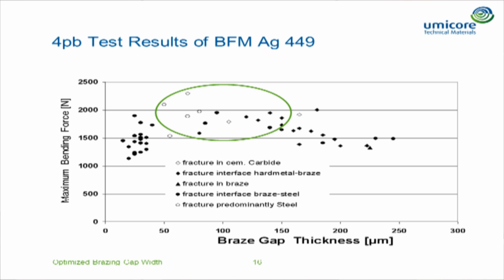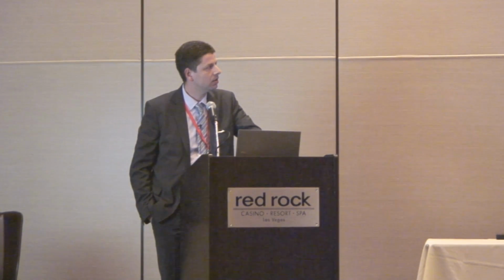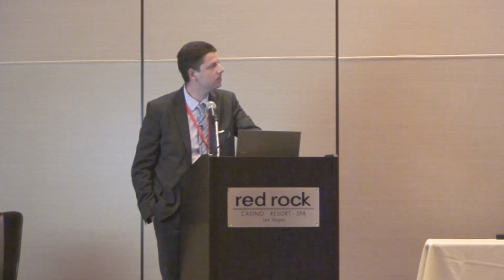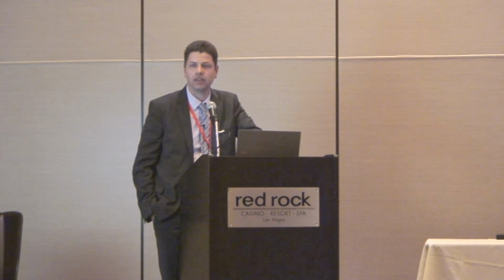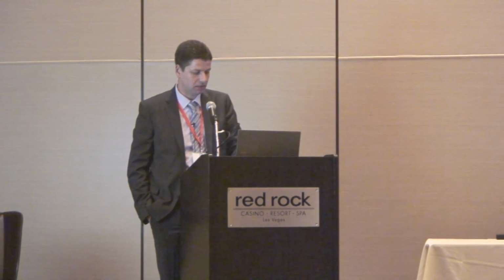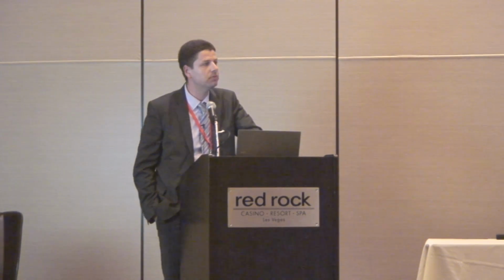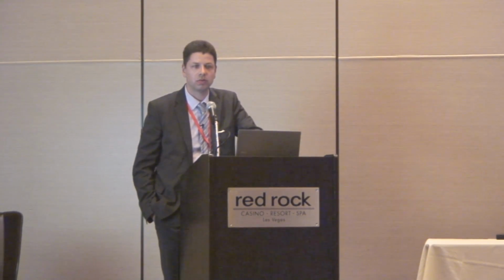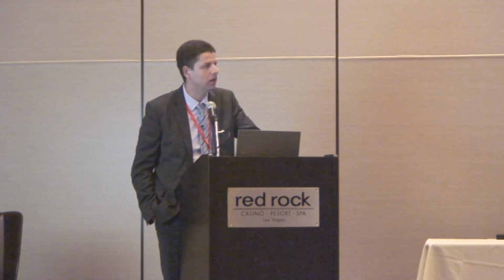We also investigated where we get the failure. When we had very small gap sizes, the failure was mainly very close to the steel side. Then we can see an area with higher values where we could not detect any failures below 1,500 Newton. And then again the force decreases, and there we get a lot of failures very close in the interface to the cemented carbide. We could say that it seems to be an area where we had the highest values, and this seems to be around 100 microns.